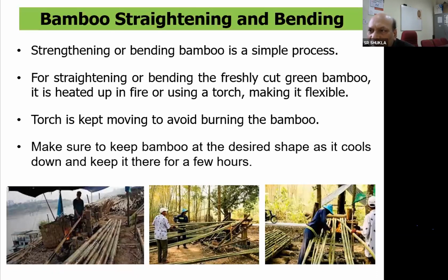We have to take fresh or green bamboo and then heat it up with fire or using a torch. Once we raise the temperature of the bamboo locally, the lignin present in the bamboo will, in the presence of water, plasticize the bamboo culm, and the culm becomes flexible. At that time we can bend the bamboo, or we can straighten the bamboo. The torch is kept moving to avoid burning the bamboo. The torch should not be focused at one point. It should always be moving from bottom to top, so that the bamboo does not get charred. And we have to make sure that the bamboo takes the desired shape.